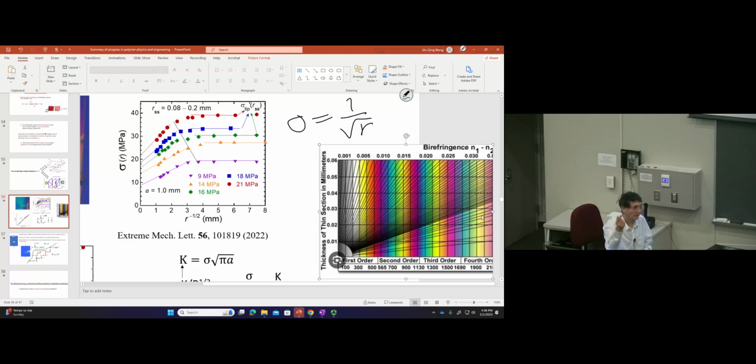No plasticity for polymer glass, no viscous effect for elastomers. Third, the polymer shows a gigantic blunting of the tip, which apparently is as if we are not aware. Because if we were aware, we would have been looking for that. So to us, we were just utterly delighted that this thing saturates.